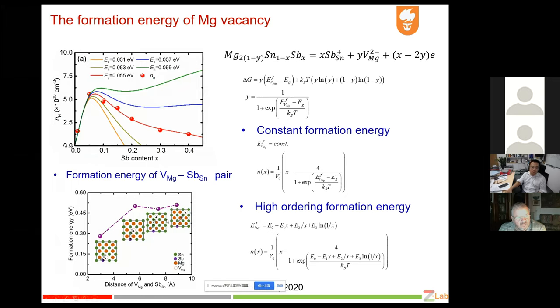We also did some theoretical calculations of the formation energy of this kind of defect pair. We realize that when the distance of this defect pair is reduced, the formation energy is reduced. That suggests that in our material, there may be very complicated defect pairs.